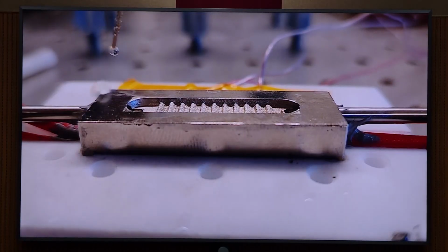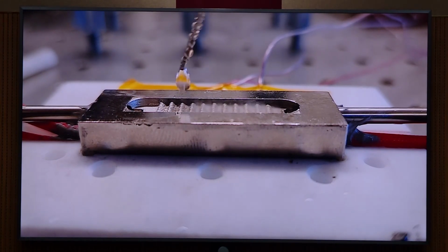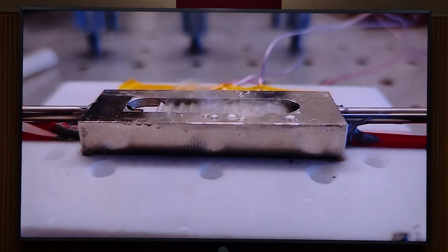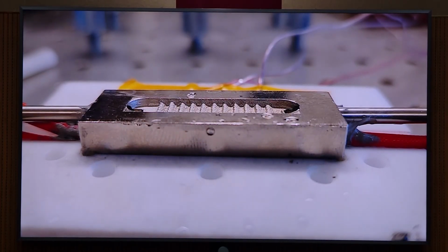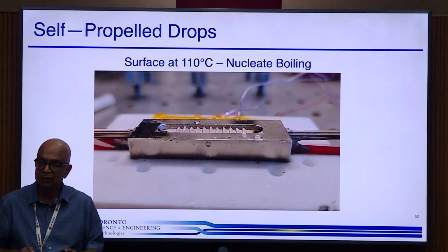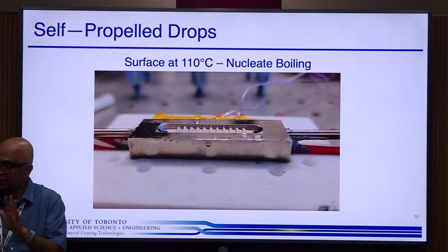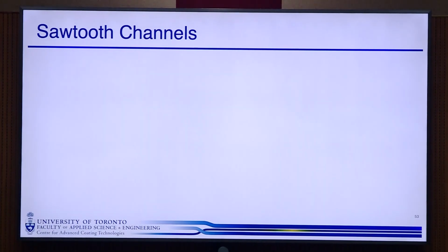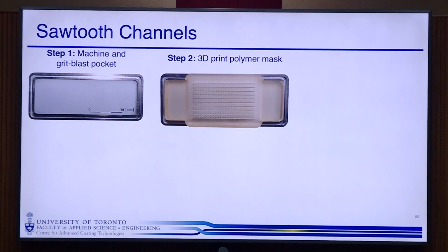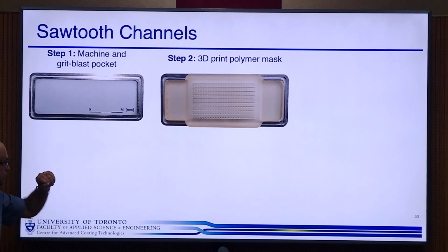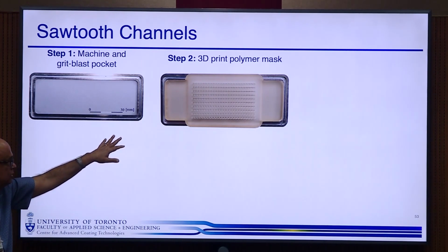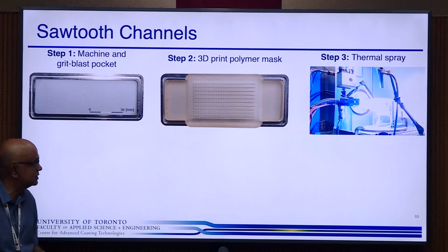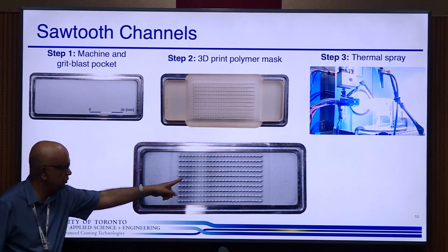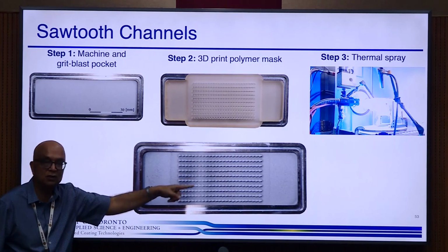And so if you put a drop on the flat side, nothing much happens. But if you put it on that, you're actually driving them quite nicely in one direction. So you can actually get a movement of the liquid even if you get boiling if you do this. So we decided, can we make sawtooth channels? So in this idea, we 3D printed a mold where there's a sawtooth structure on the walls, right? And you spray this, and what you end up with are the channels, except now they have this little sawtooth structure.